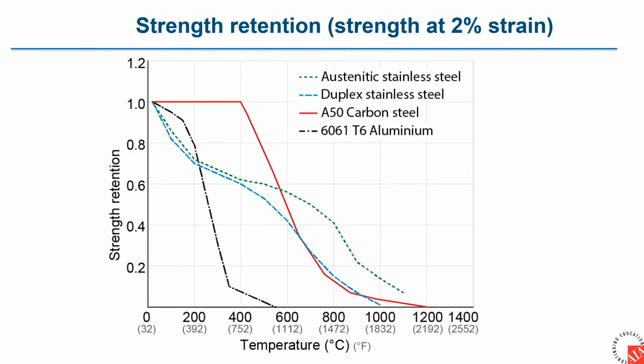At a high level, this summary shows you the strength retention of aluminum, carbon steel, duplex, and austenitic stainless steels. You can see that the strength of the stainless steels drops off at the lower temperatures relative to carbon steel, but once we are above 600 degrees Celsius or 1,112 degrees Fahrenheit, the austenitic stainless steel is better than carbon steel. That's specifically molybdenum-containing austenitic stainless steels, like type 316, because the molybdenum does provide an advantage.